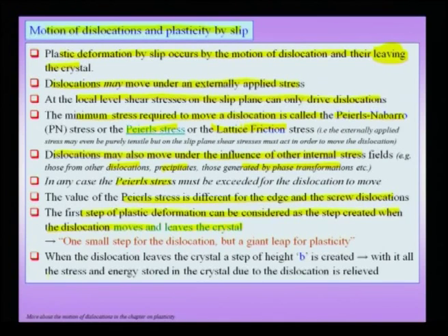Now it is important to note that this is one small step for a dislocation, but a giant leap for plasticity, because this small step which we are considering here lies at the heart of all plastic deformation. When, as I pointed out, even this dislocation leaves the crystal, a step of height b is created. With this, all the energy and stress stored in the crystal due to the dislocation is relieved, and therefore now